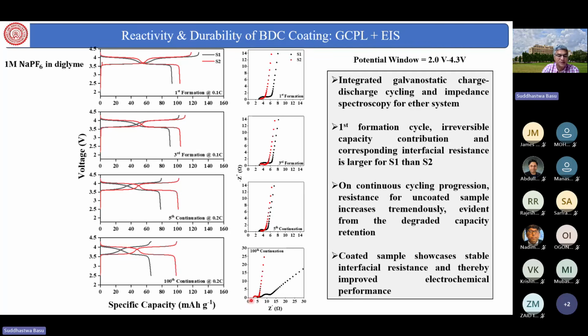The polarization resistance is high in the case of black compared to the red. Okay, so S1, S2, S1, no BDC is black, so polarization resistance is high. Red is where there is a BDC and polarization resistance is low. So that means it is protecting the material.